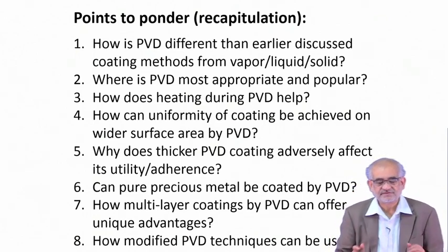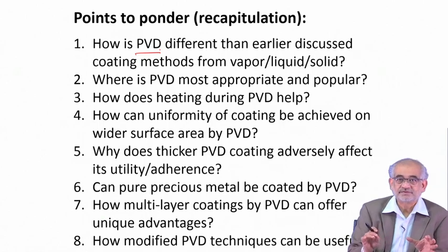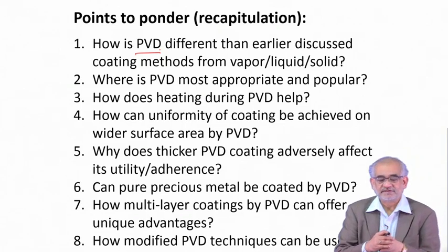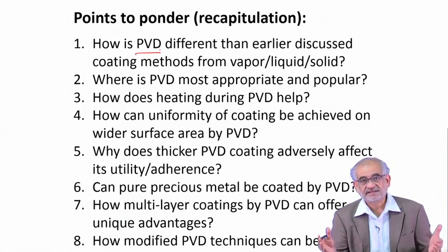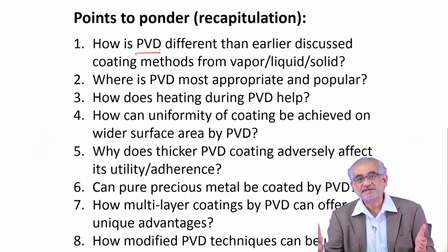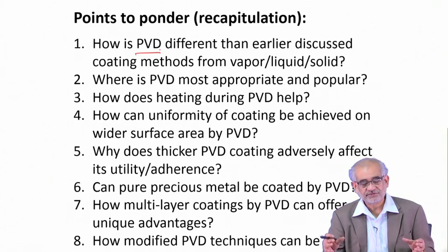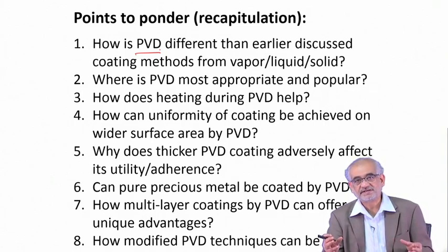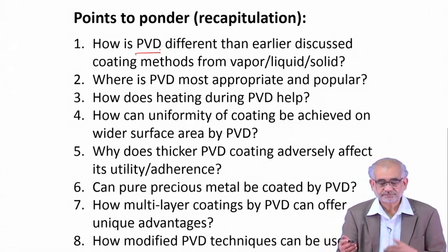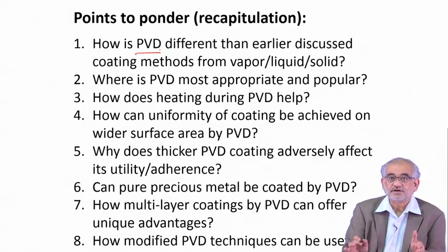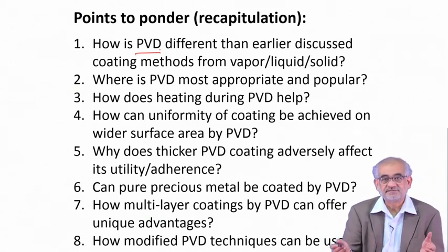To recapitulate: we have started discussing thin film coatings, and one of the most versatile methods is physical vapour deposition, where the process involves operating a high vapour pressure material in the vapour state and then allowing it to deposit on any colder substrate. If vapour reaches the chamber surface it also gets deposited there, which we do not want, so we create a certain trajectory such that the component is placed on the path of the vapour. There is no change in composition — we exactly deposit what we have in the target.